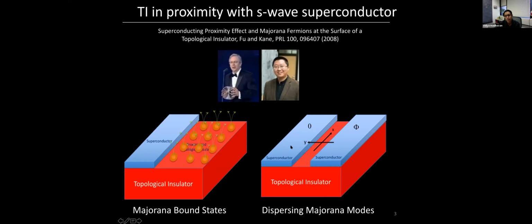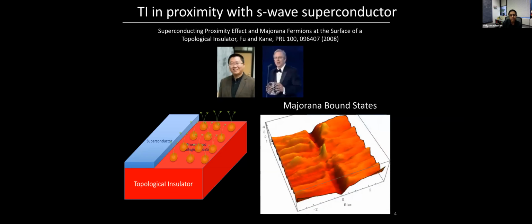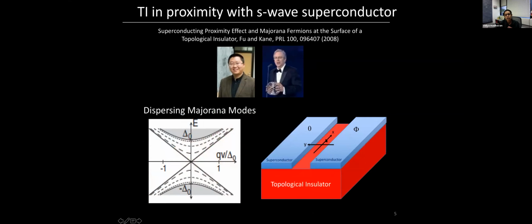Also, by some clever engineering, if you could put two superconductors with a pi phase shift, or in fact, as it turns out, any phase shift, on top of this topological insulator, then at the boundary between these superconductors with different phases, you expect to see propagating Majorana fermions. So the signatures of these vortex-bound states would be seen, for example, in STM spectroscopy as a zero bias peak inside the superconducting gap. And if you were to achieve this geometry where you have a pi or a phase shift between two superconducting regions, then at the boundary, you should see dispersing Majorana states. And these Majorana states should be helical states, and they should have linear dispersion.